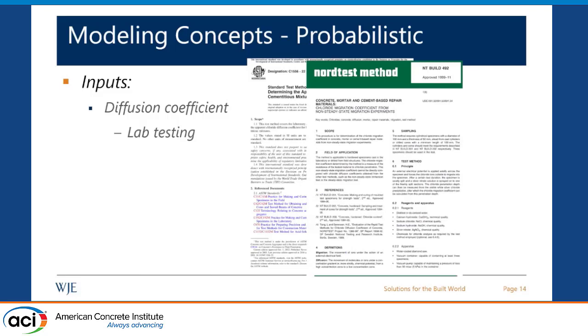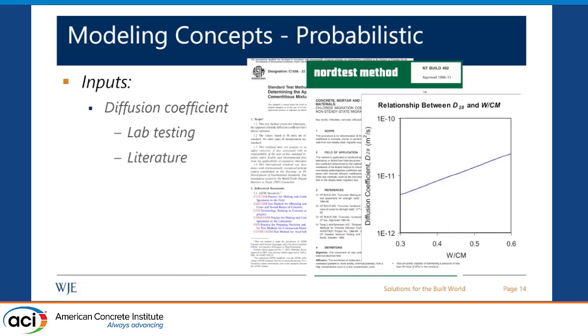You can also use the NT Build test, which defines the chloride migration coefficient. It's a little bit different from the diffusion coefficient, because in this test you drive voltage through your sample, and you measure how far the chloride penetration got in your sample, and based on that you can define the chloride migration. Or you rely on data presented in the literature. So here, for example, the data is correlations presented in the manual for Life 365, based on extensive literature of bulk diffusion testing, and they have a correlation to define the diffusion coefficient based on the water-cement ratio.